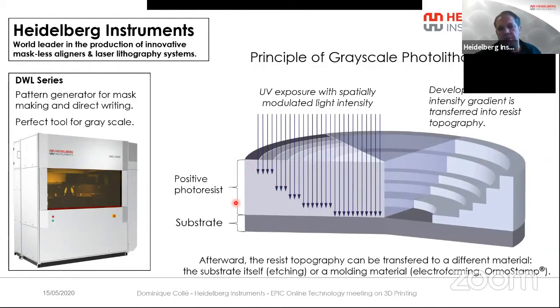So here we have a positive photoresist, and the thickness that we are working on is basically between 0 to about 100 micron. And it's resting on a flat substrate that is typically a wafer or glass sample. Afterward, the resist topography can be transferred to a different material by etching. So we can etch the wafer or the glass underneath the photoresist, or by molding, like with electroforming, or by molding with the OrmoStamp, for example.